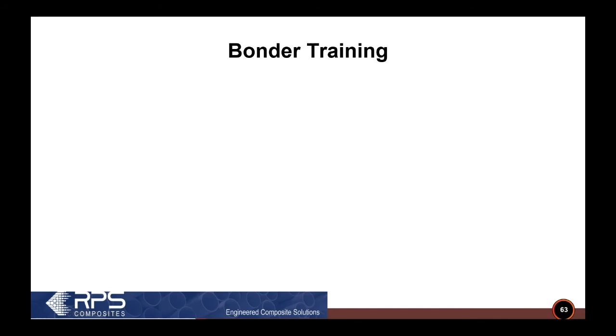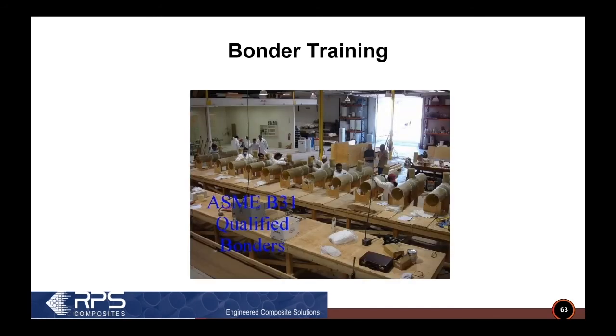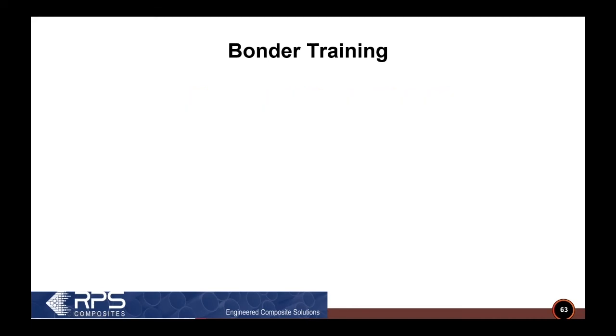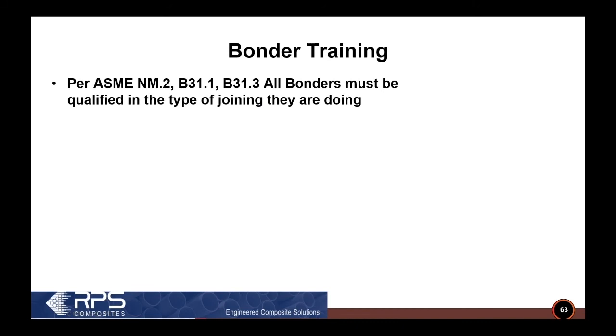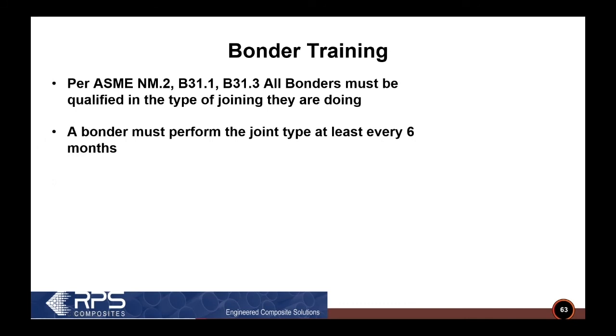Well, I mentioned that you have to be qualified to do FRP piping, and here you can see this is how we do it in our shop. So here's some qualification that went on at one of our shops. The guys would do a qualification spool, and that's what it says in ASME B31.1, B31.3, and NM2. So if you reference any one of those three codes, you're actually saying that all the bonders must be qualified. And to qualify, a bonder has to do a joint, make a qualification spool, and keep doing those joints at least once every 6 months, and then their qualification remains current.